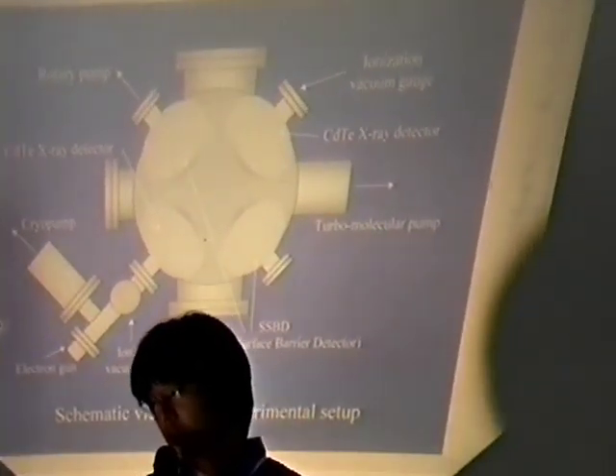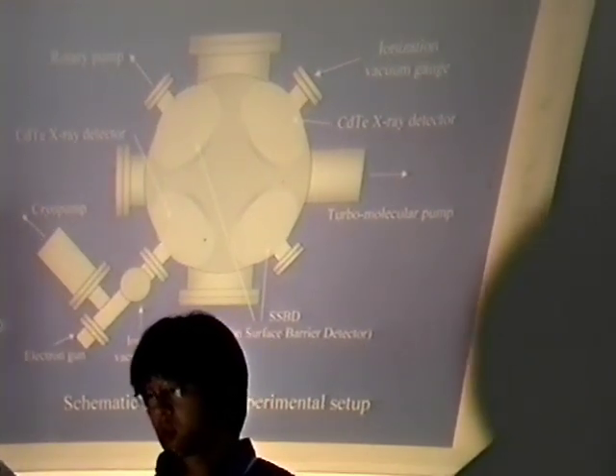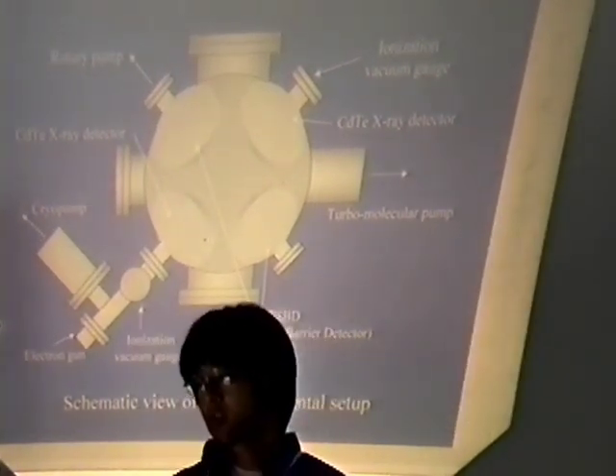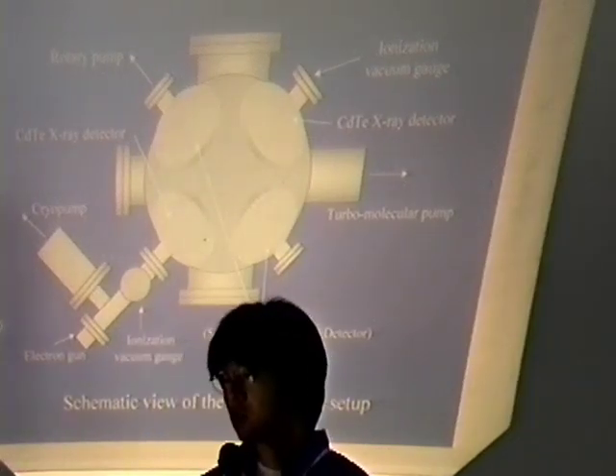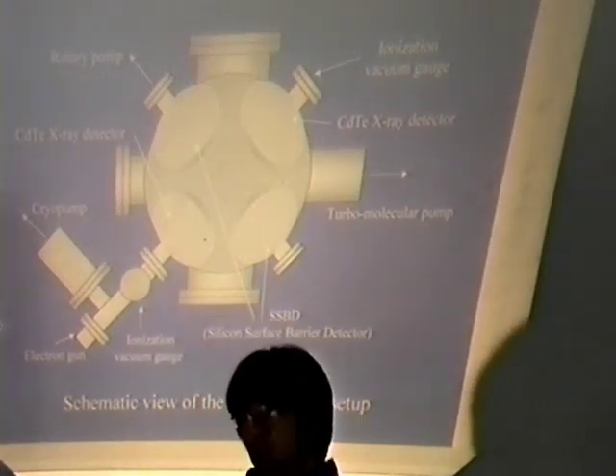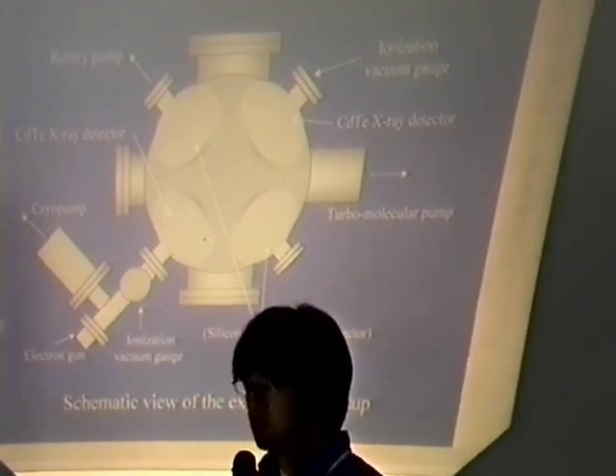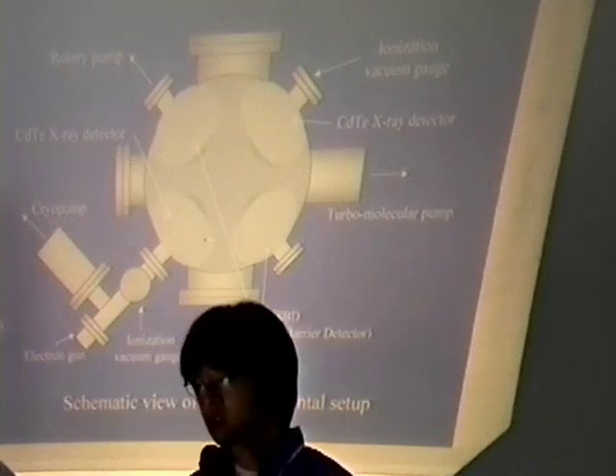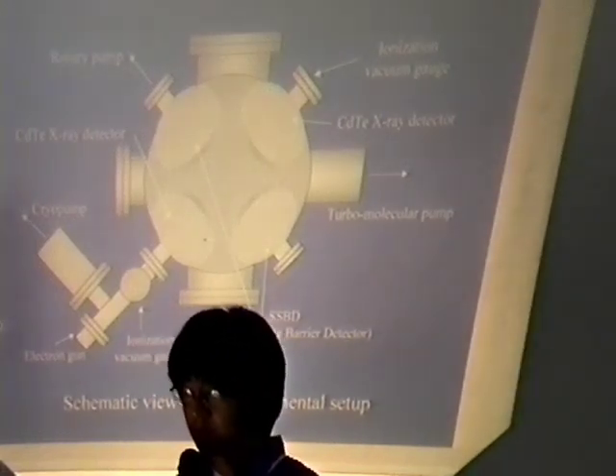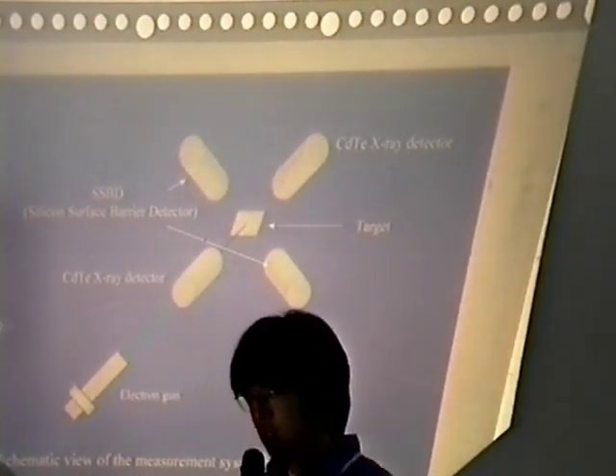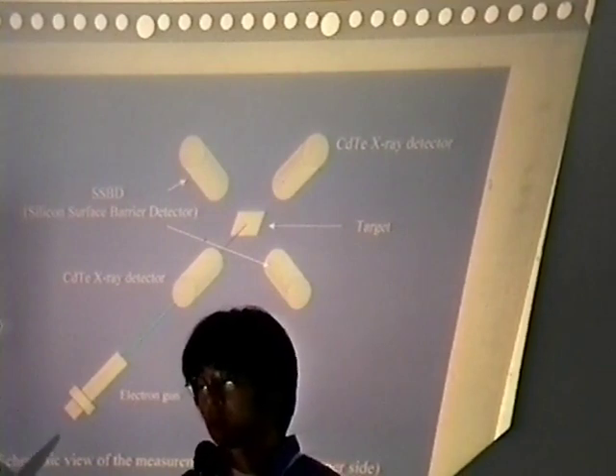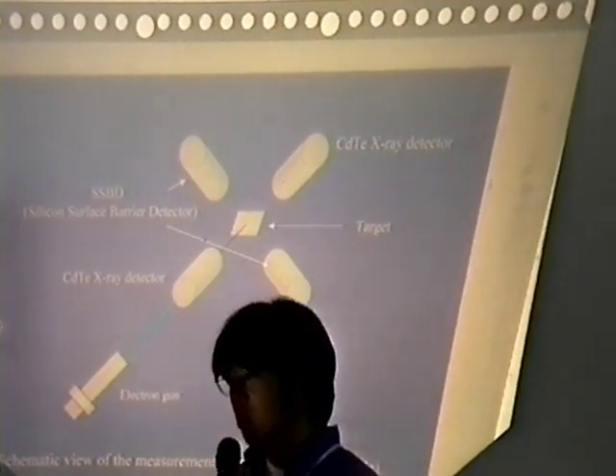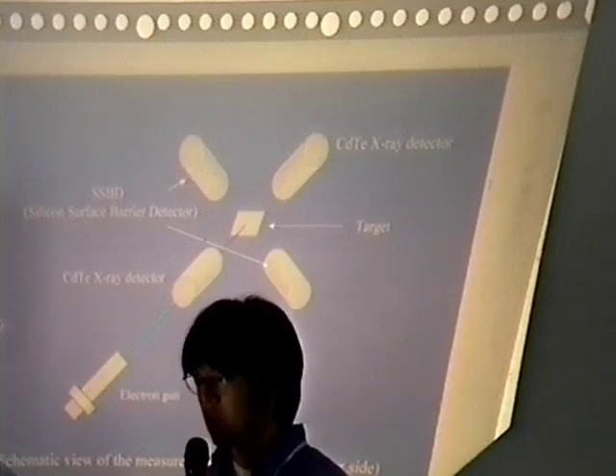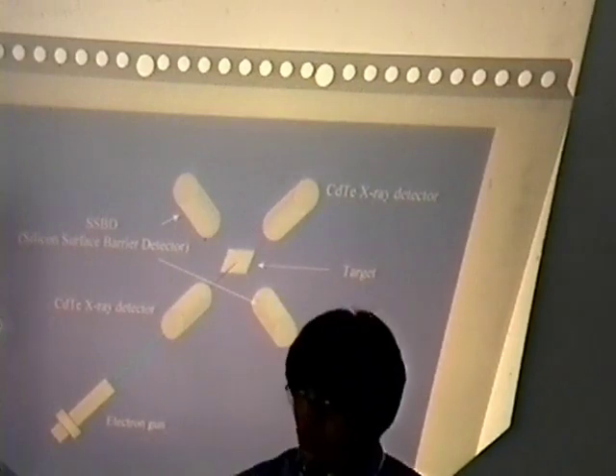This figure shows the schematic view of the experimental setup. The detectors were attached to the chamber like this, and the electron gun was here. The beam energy is about 3 keV, and the current is about 3 microampere. And the beam diameter is about 1 millimeter on target. Two identical SSBDs were set symmetrically to the electron beam, and 2 identical cadmium telluride X-ray detectors were set like this.